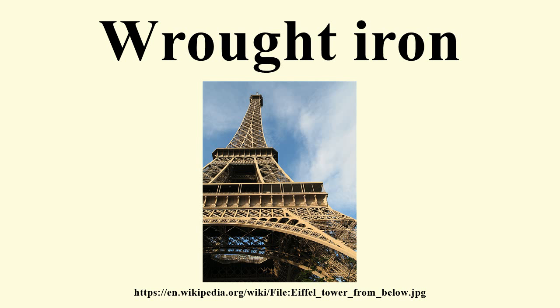Decline. Steel began to replace iron for railroad rails as soon as the Bessemer process for making steel was adopted. Iron remained dominant for structural applications until the 1880s because of problems with brittle steel caused by introduced nitrogen, high carbon, excess phosphorus or excessive temperature during rolling, or too rapid rolling. By 1890, steel had largely replaced iron for structural applications. Sheet iron had good properties for use in appliances, including being well suited for enameling and welding, and being rust-resistant.